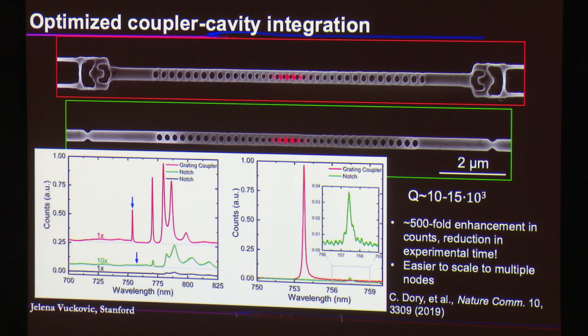Theoretically, it can have up to 50% efficiency for vertically symmetric structures, because you always re-radiate half up and half down. But we were here also limited by minimum feature sizes. In our diamond fabrication, minimum features are 100 nanometers, and I think they're probably a little bit better now. We also wanted to do it in something that's about 1 by 1 micron. If you have the notch coupler with 1% efficiency, you wait 10 seconds, and you start seeing something that's probably a cavity. That's how you would do your experiment. Then you integrate longer, and if you have enough signal, you can actually do some measurement. And here, after 1 second, so after 10 times shorter integration time, you see much stronger signal from the cavity. So you can, in principle, reduce your experimental time by a factor of a few hundred.